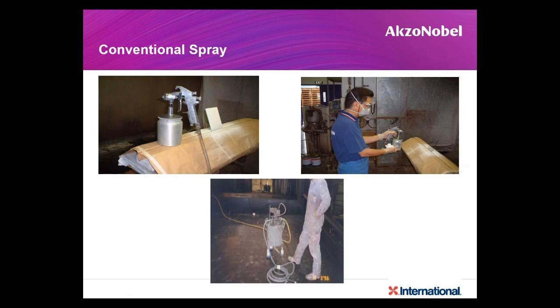And more importantly, when you apply by conventional spray, you have to thin the paint. So thinner consumption will be very high. In high performance coatings, you use conventional spray, especially to apply inorganic zinc silicates with an additional equipment called the pressure pot. Because zinc will be heavy material, it will settle down. You got to mix it continuously. So you use something called a pressure pot.